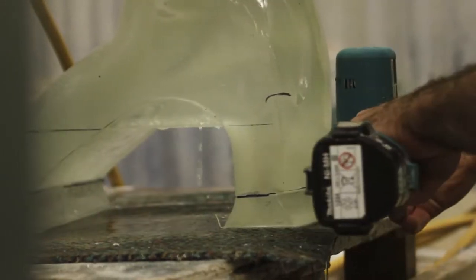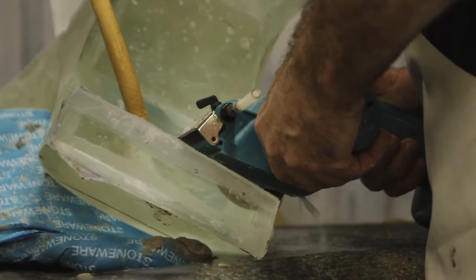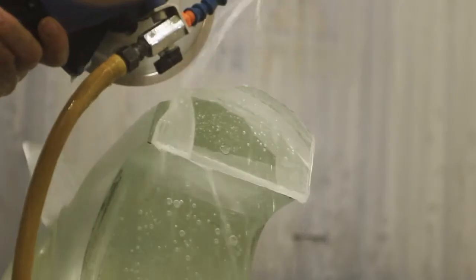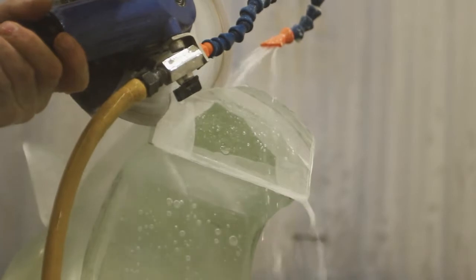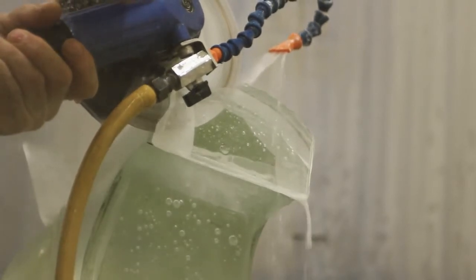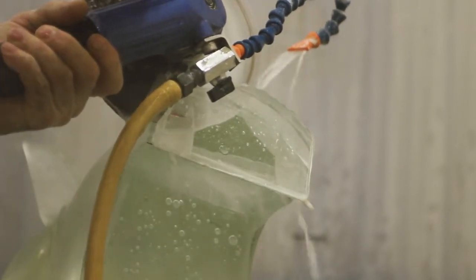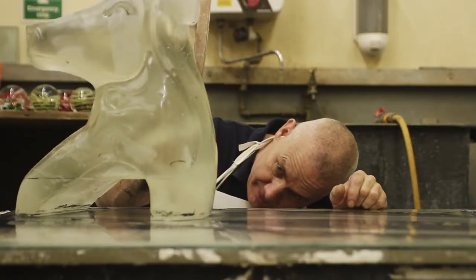There's a funny measurement between the flat surface of the stag to the floor. It all has to be very precise and leveled, because the whole sculpture goes on top of a specific fixture that Glenfiddich has made. So it all has to be very, very flat, and we hand lap it. We just take a huge sheet of glass, drop a bit of grit, silicon carbide, and we hand lap it.